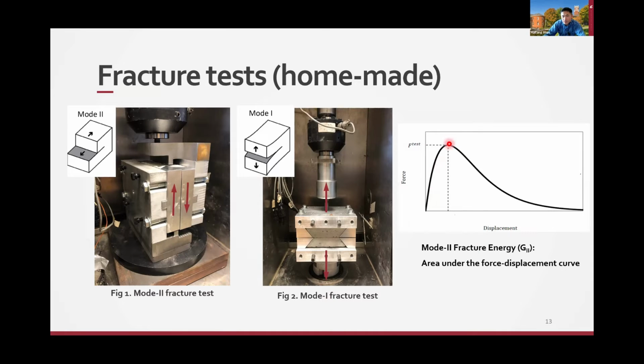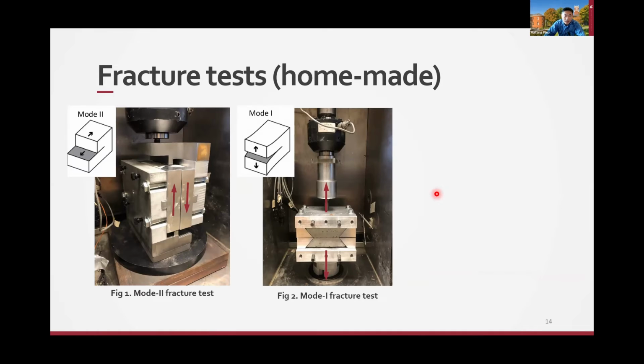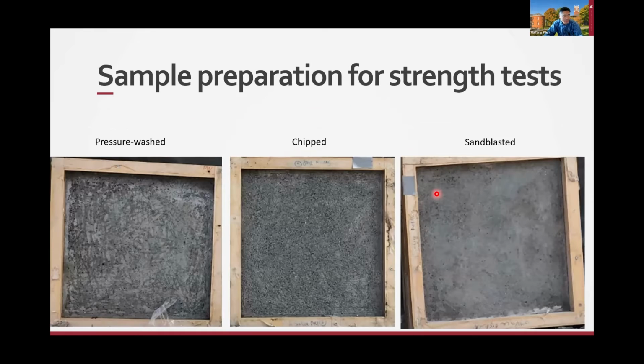So this is a typical test result. When you break the sample, you have this peak load and then failure, right? And from there you can get the fracture energy of the bond. The other test is